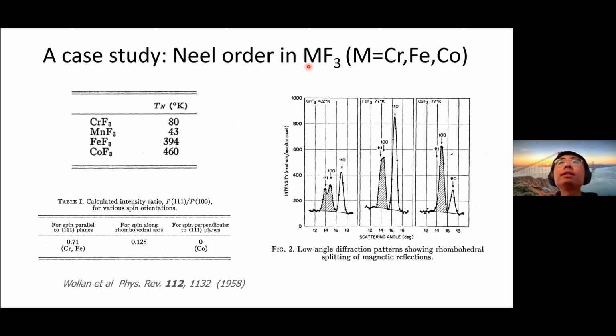This family is known as MF3, the transition metal trifluorides. In these transition metal trifluorides, the transition metal can be chromium, iron, or cobalt. These are of interest to us, and one reason we study them is because they all seem to have fairly high transition temperatures, giving us an ideal platform to realize topological magnons at higher temperature, even at room temperature sometimes.